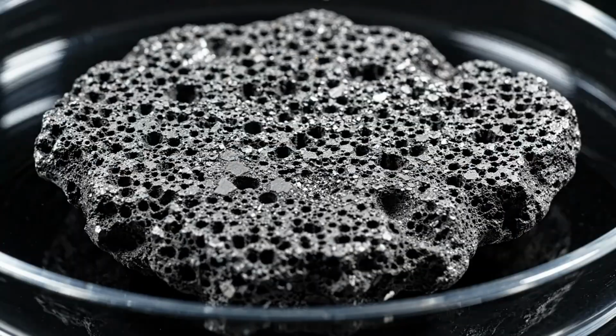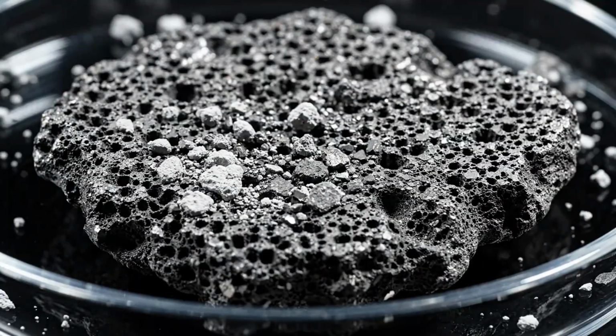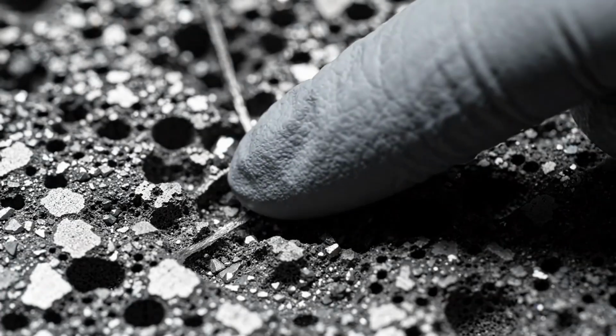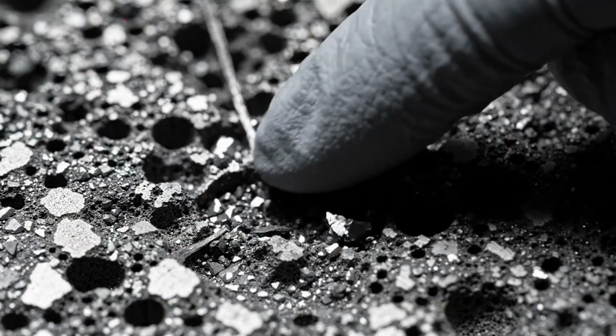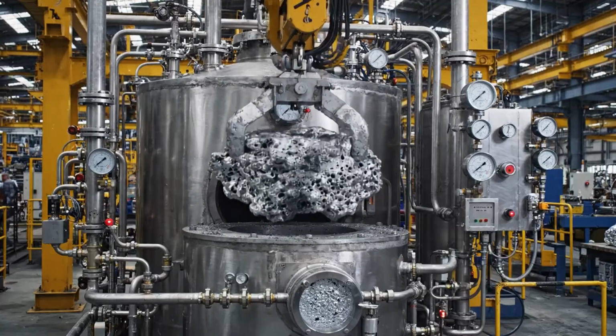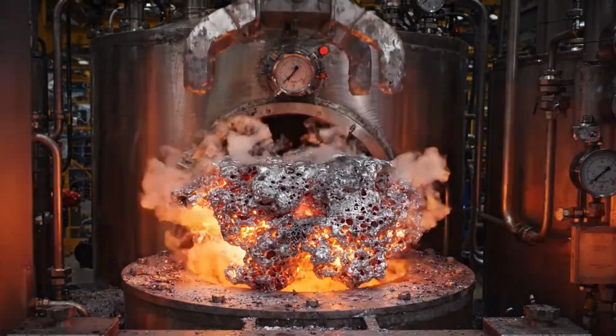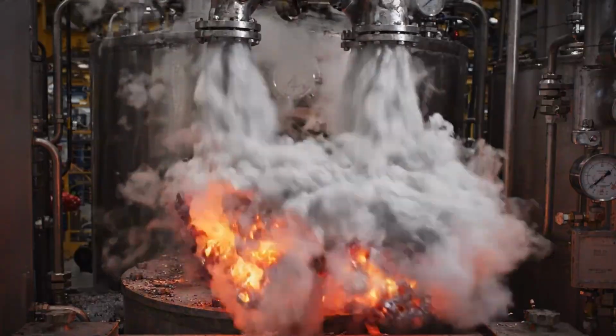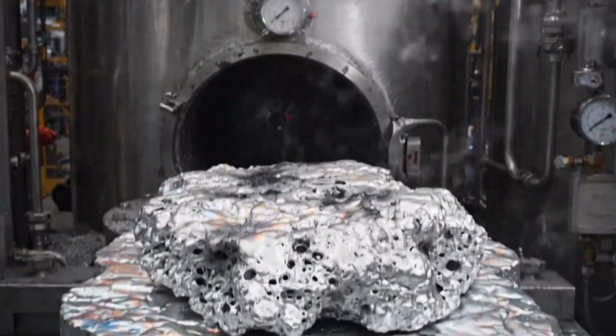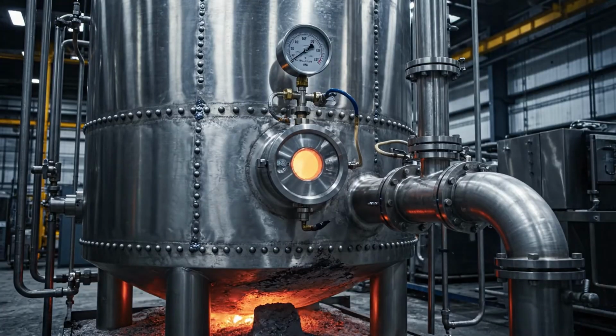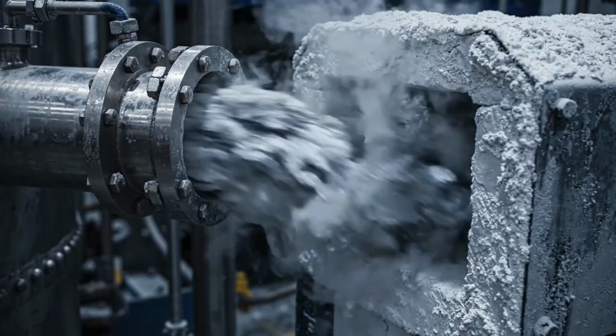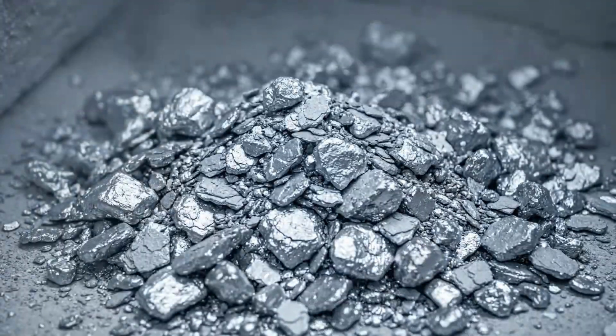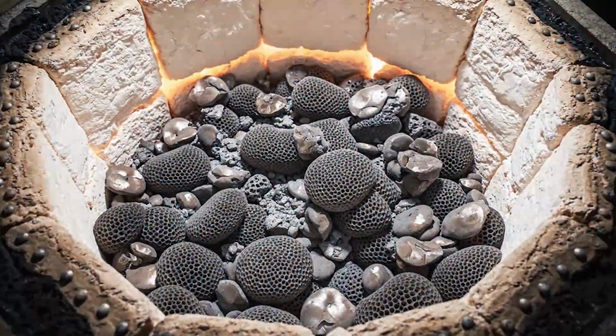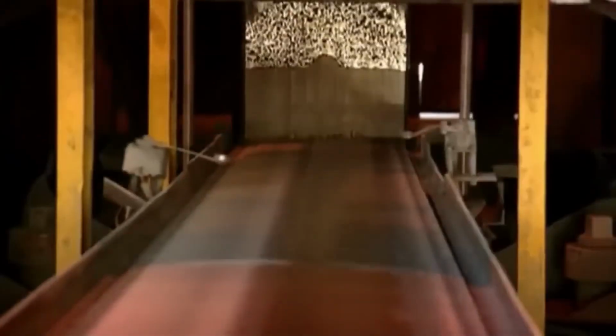The titanium does not emerge as a perfect liquid ingot. It appears as a porous, irregular, grayish mass called titanium sponge. The name sponge aptly describes its appearance. The metal grows inside the reactor as a porous structure, mixed with salts and magnesium remnants. It is not a solid piece or a uniform powder, but a brittle block contaminated with reaction byproducts.